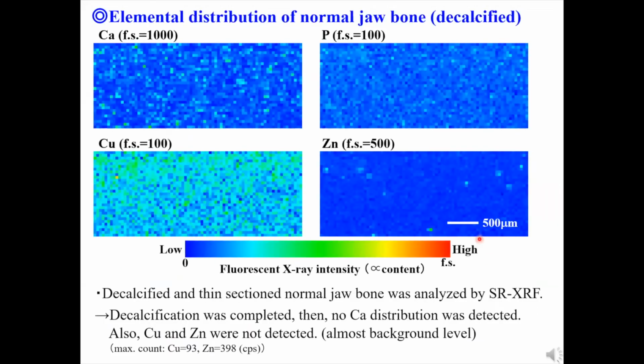Those images are the typical elemental distribution images in the normal jaw bone. In those images, reddish color means higher concentration and blue is lower. The specimens were decalcified and thin-sectioned. In the decalcification process, the calcium phosphate was completely removed, so calcium and phosphorus were not detected. Other cations contained in the bones, such as zinc or copper, are usually contained as substitutional elements at the calcium site of the bone apatite. Therefore, those trace cations were also removed by the decalcification and were not detected.